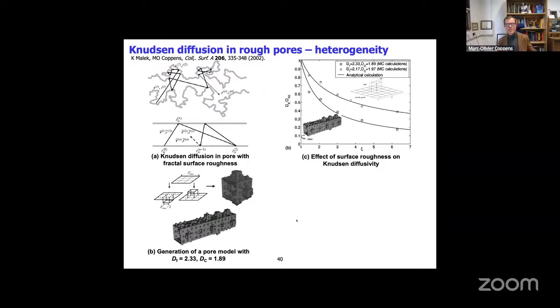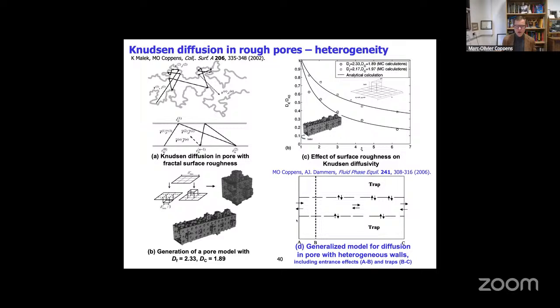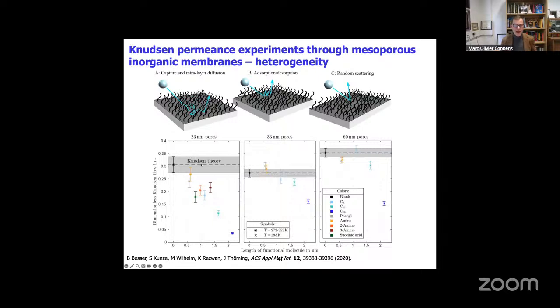Now, if you go back to that image I showed earlier of rough pores, we can coarse grain that whole image and consider this as a channel with effective heterogeneity. That could be geometric, it could also be chemical. So there's a more general model where you can consider a channel with traps on the sides. And that's something we proposed in this paper in honor of John Prausnitz, in fact, published in 2006. And very recently, this was compared with experimental work on Knudsen permeance experiments through mesoporous inorganic membranes by the group of Rezwan and Thöming and colleagues.